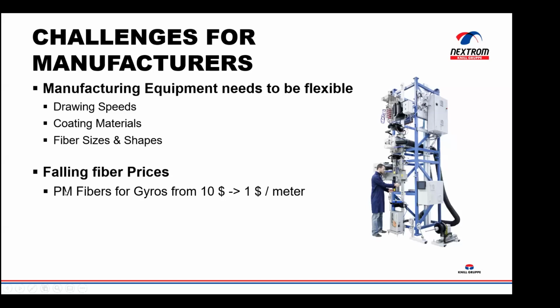So here you can see this. I did have the data that the polarization maintaining fiber for gyroscopes has fallen from $10 per meter to $1 per meter. And I know there's been somewhat of a similar drop in prices for rare earth doped active fiber, but I struggle to find a good chart showing it. Because I think part of the problem is that there's just too many varieties. You can't just define an active laser fiber. You have different core sizes and different dopants, different lengths. Everything can change.